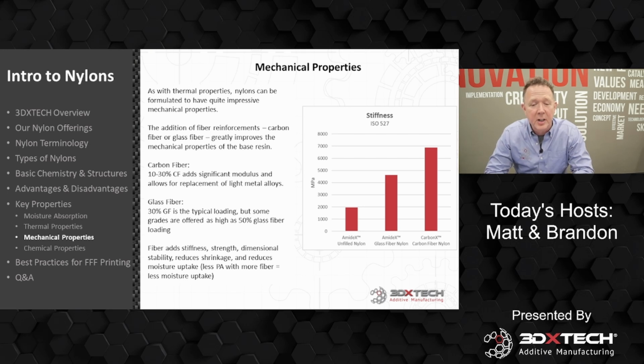So here's a good example. You put carbon fiber into the same material, you end up with a tripling of the mechanical property. This one here specifically is tensile modulus. Glass fiber is a little bit less efficient at making things stiff, but it adds other things. You can put more glass into it. You end up with better dimensional stability, better strength, not necessarily stiffness, and a whole lot less moisture absorption because you're actually displacing a whole lot of nylon, because you can more heavily load it. Same could be said with other reinforcements that change properties, whether it's, again, talc, mica, some of the wear additives that we put in, other companies might put in, like molybdenum. They do different things to make it stiff. So the mechanical properties of these materials can be greatly varied by what additive packages you put in.